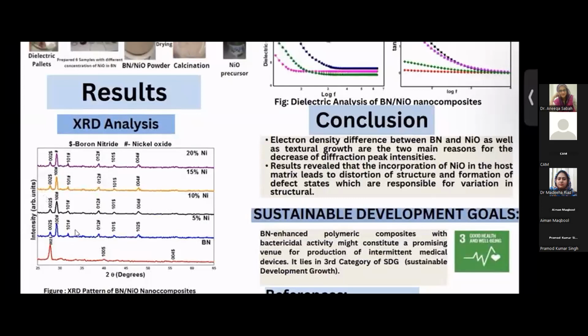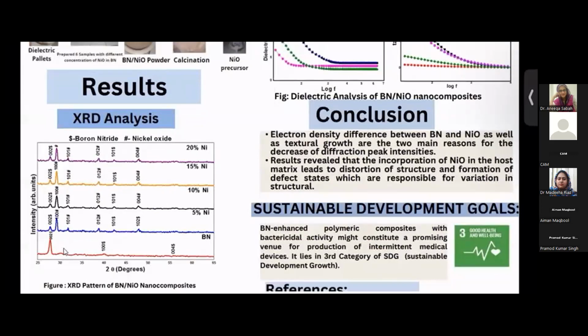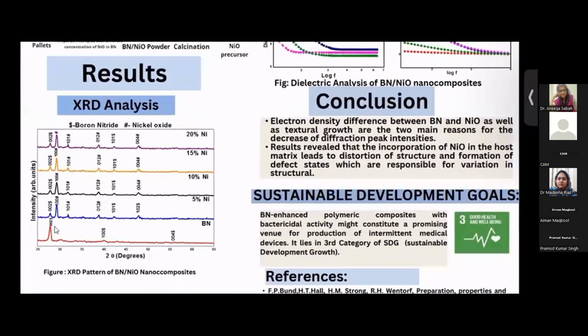XRD patterns were compared with the standard ICDD card or JCPDS card of boron nitride and nickel oxide. A comparison of the obtained XRD pattern with the standard card confirmed the formation of boron nitride nickel oxide phases in the synthesized nanocomposites. As you can see from the graph, the red line with the 002 peak is for boron nitride. The blue peak is the 100 plane for the nickel oxide concentration.